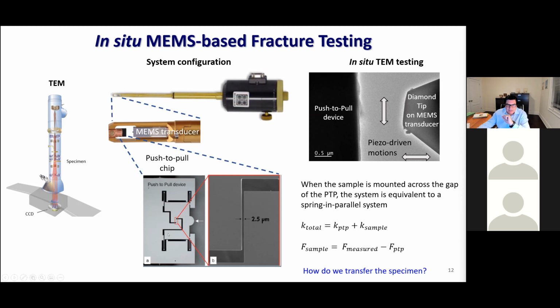The way that this works is that there is this microfabricated silicon chip where you have a region of the chip that is connected by these folded beams to the fixed stationary part of the chip. So if you were to compress here, you will displace this part and then introduce a tension in a sample that is located across this gap. And this is the gap that we are seeing. And you can then measure the force and subtract the force that goes to the folded beams and obtain the force on the sample.